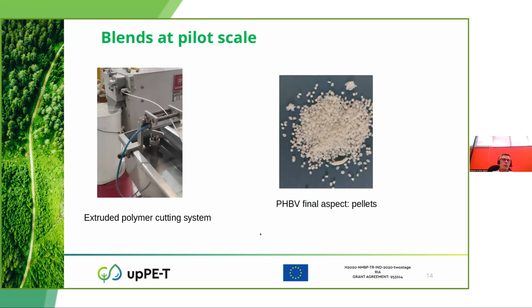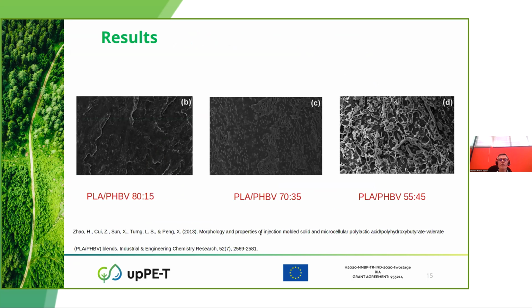However, to assess the degree of homogenization, we must analyze these pellets. How to analyze this pellet? With a scanning electron microscope, we can see several pictures from several blends with different PLA and PHBV ratios, and you can see how the two phases are dispersed within each other. Good dispersion and homogenization of the two polymer phases is observed in all cases.